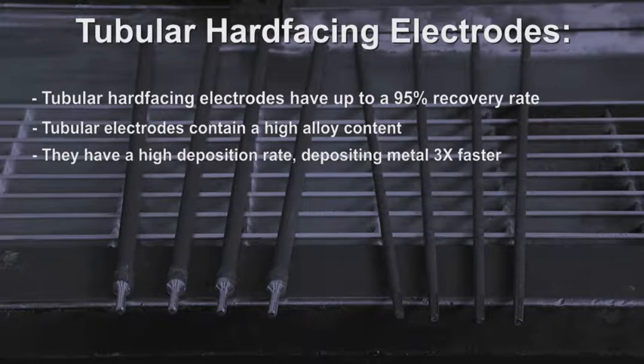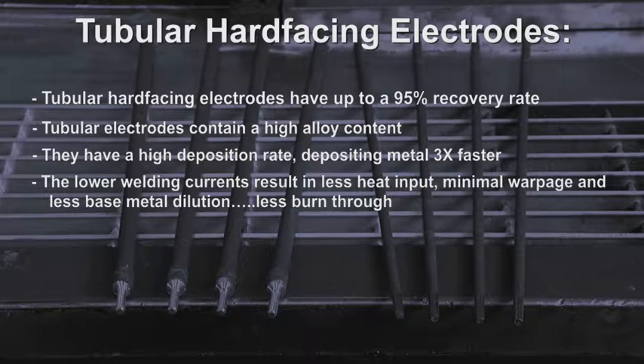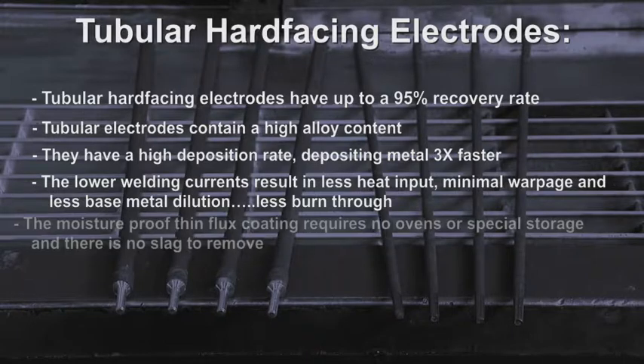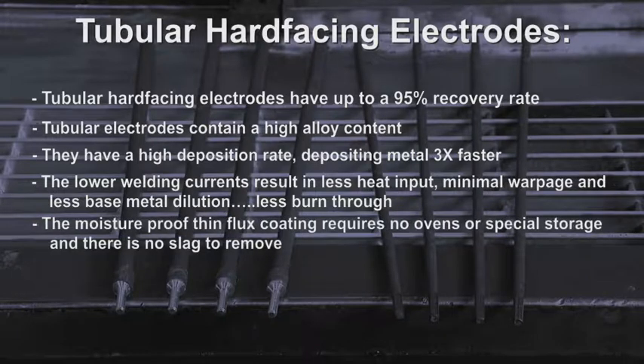They have a high deposition rate, depositing metal 3 times faster than ordinary electrodes. The larger size particle increases the surface area of the carbides. The lower welding currents result in less heat input, minimal warpage, and less base metal dilution, including less burn-through. The moisture-proof thin flux coating requires no ovens or special storage, and there is no slag to remove.